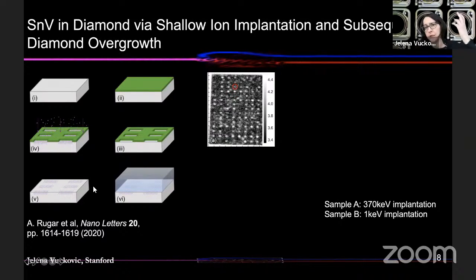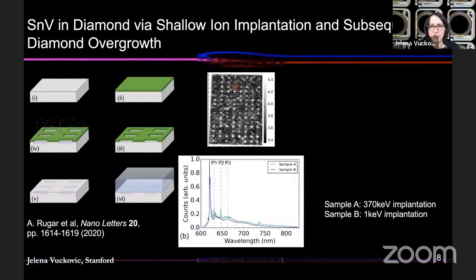Of course, when you implant them at low energies, they're just very close to the surface. And that's not something that you would like to have in practical devices. You don't want to suffer any effects from surface interactions. So at the very end of the process, after we do ion implantation at desired positions, we actually grow using CVD, chemical vapor deposition. We grow synthetic diamond of high purity to cap everything. That way we end up with these ions in the middle of a membrane that is less than 200 nanometers thick. And here you see a regular array of these implanted tin atoms in the structure.